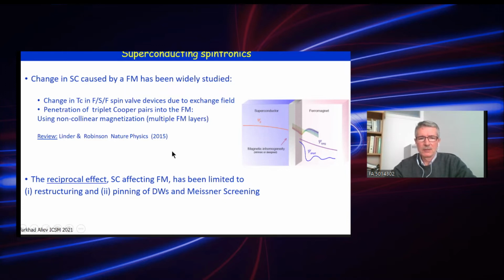Here we have a review. Also, recently a reciprocal effect, where superconductivity affects ferromagnetism by changing its magnetic crystalline anisotropy, has been predicted. Before, such effects were mainly restricted to restructuring and pinning of domain walls and Meissner screening.